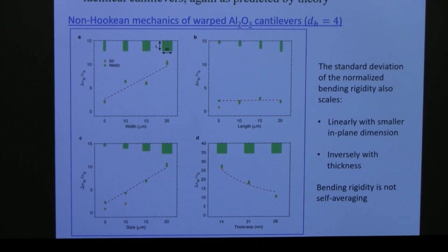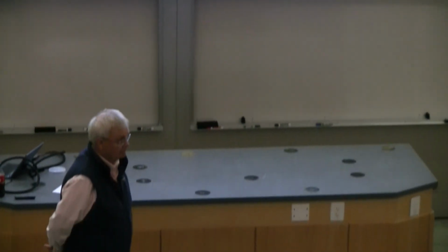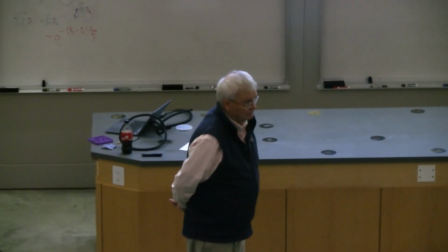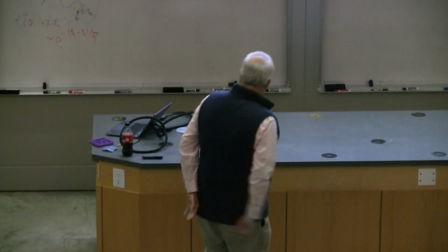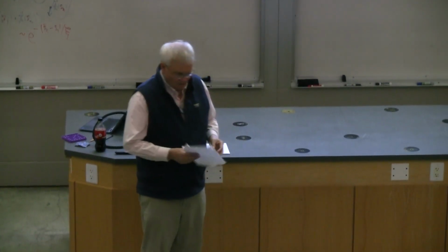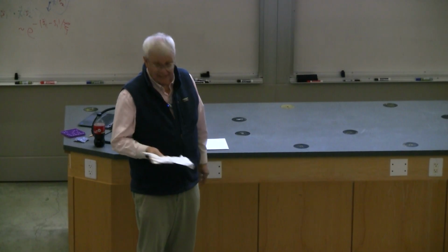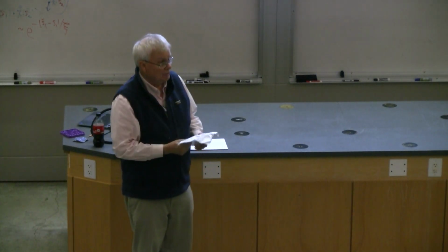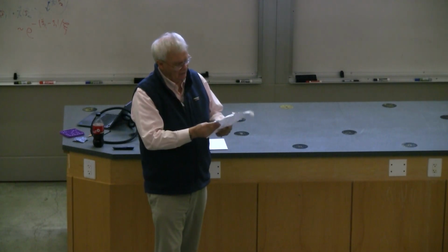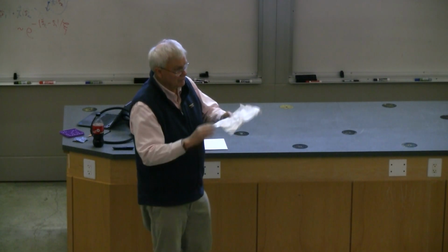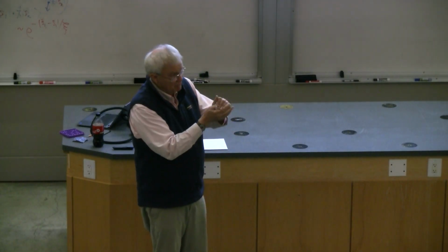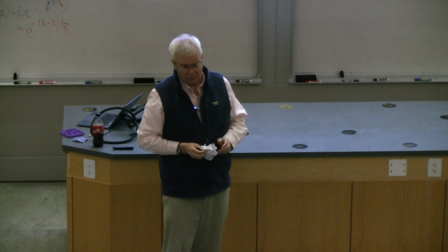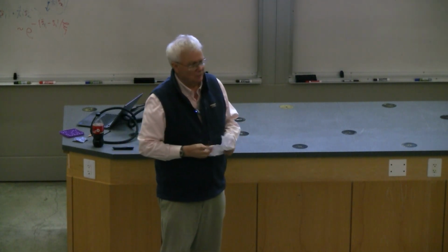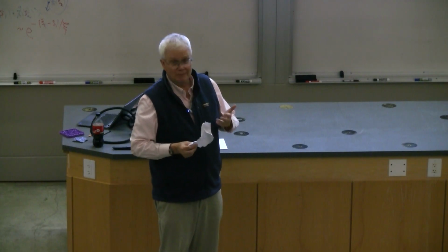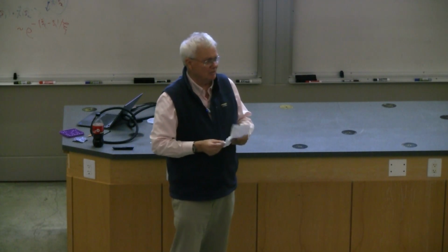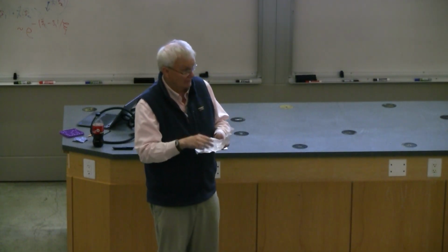Sorry, I didn't quite follow the crumpled sheet part. How does the crumpled sheet sustain itself? Is it locally plastically deformed? Oh, okay. So the crumpling transition, much as I would wish otherwise, has never been observed in graphene. If you take a simple back-of-the-envelope calculation and ask when the entropy of the fluctuations of the normals in this flat phase is going to be enough to produce that, the answer is about 20,000 degrees Kelvin. That's very hard to obtain in a lab, even at Stanford. And if you got up to 20,000 degrees Kelvin, you'd be breaking the covalent bonds.